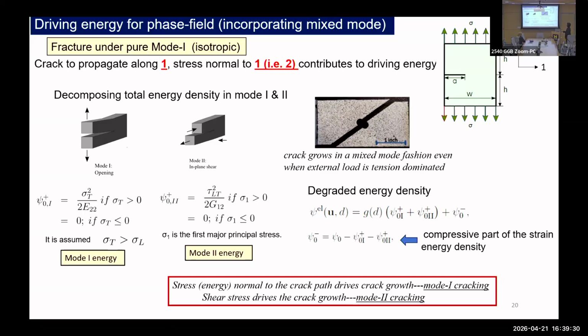And we can simply write down a strain energy density based on the transverse stress and the transverse modulus, like this. Okay. Similarly, if the crack is to propagate under mode 2, then the shear stress and the corresponding shear modulus will be used to compute the shear energy part, or the mode 2 energy part of the driving force, okay? And of course, we have to have these criteria to ensure that fracture happens only in tension-dominated situations. For the shear case, we depend on the principal stress calculation: if our major principal stress is greater than 0, then it will be a non-zero term, otherwise it remains 0.